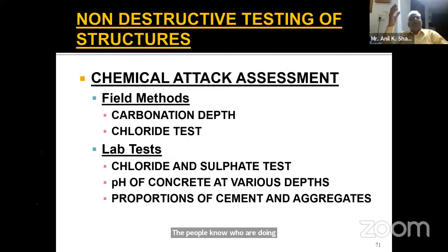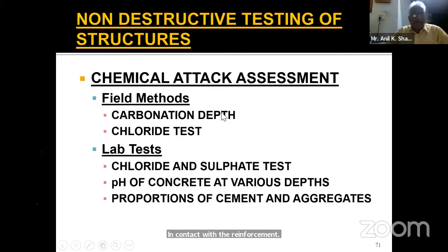Then now is the chemical. You see, reinforcement corrosion is directly impacted by the chemical quality of the concrete. Reinforcement corrosion starts when the level of alkalinity of the cement paste goes down. So directly measuring the pH value of the cement paste in contact with the reinforcement gives you the likelihood of the corrosion susceptibility of the reinforcement. So chemical attack assessment can be done using the field methods, by using the phenolphthalein test, using carbonation depth, and using the chloride test by taking the samples from different depths of the concrete.